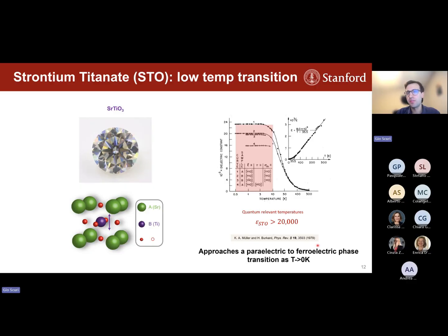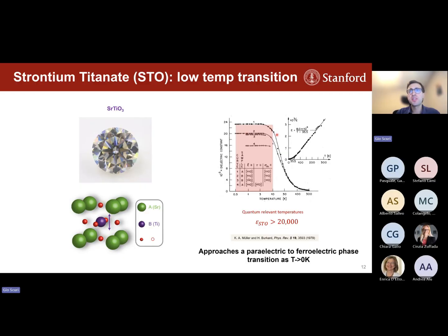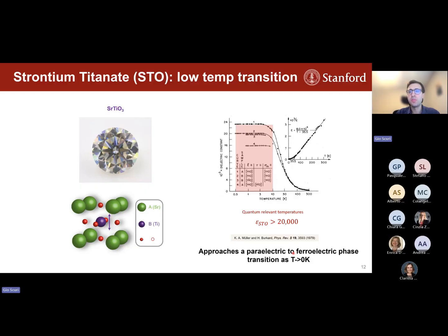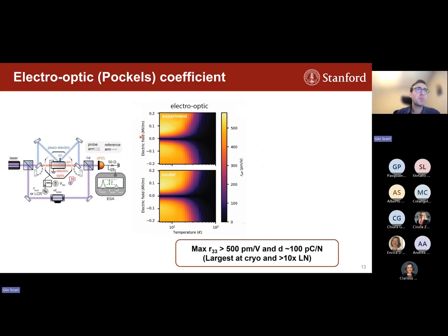It's a material that actually has been studied for quite some time in the context of material science and condensed matter. As you can see, even from studies in the late 70s, there were dielectric constant studies that show that there is a sharp increase as you approach low temperatures, and that indicates that the system is close to a paraelectric to ferroelectric transition, but never fully undergoes the transition because it stays in a so-called quantum paraelectric state. And so we've been able to measure via Mach-Zehnder interferometry measurements the electro-optic coefficient of this type of material as a function of a DC bias electric field, which we still need to break the symmetry in the system because it is a Chi-3 system, and the temperature.